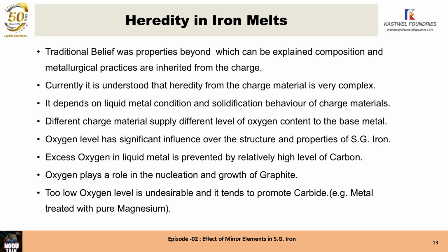If sulfur is too low, we end up with non-spheroidal graphite shape. If sulfur is too high, we end up with flake graphite or vermicular graphite. If oxygen is too low, we end up with inverse chill. So there are limits to which we can reduce the oxygen. Sulfur is not much of a problem, but oxygen control is a problem in SG iron. So this is why we always say, for making good quality SG iron, keep your raw materials and process control very, very closely controlled. Changing raw materials or process variations causes problems in SG iron quality.